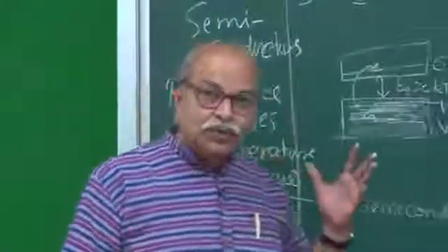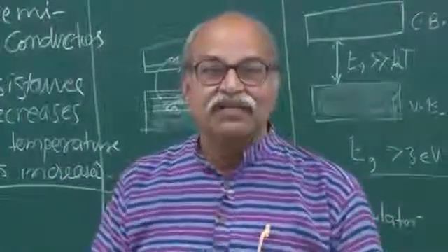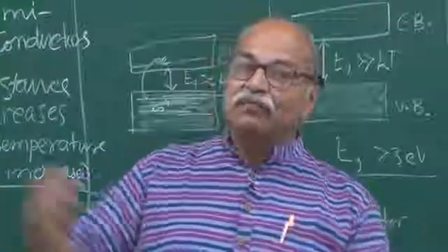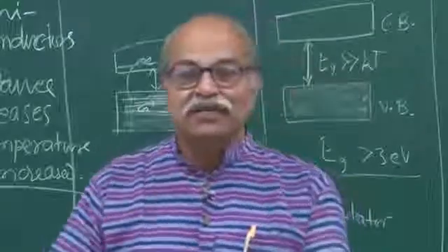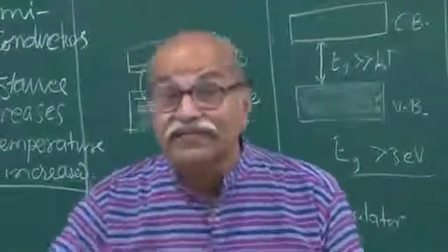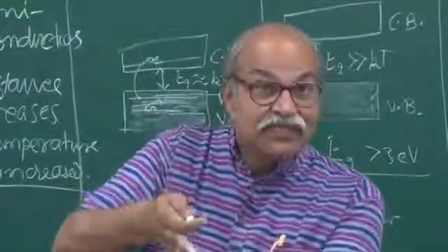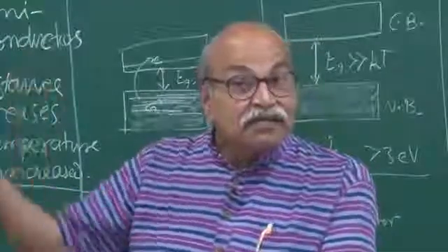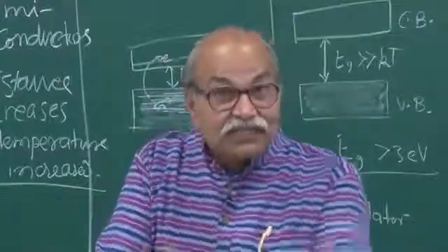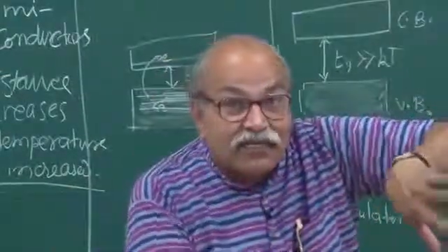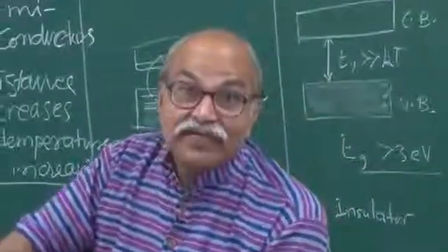This can be used to identify experimentally which material is a conductor and which material is a semiconductor, or if in some process there is a transition from metal to semiconductor or metal to insulator, going towards insulator. If there is some kind of transition, that transition can be identified experimentally by looking at the temperature dependence of the resistivity, and you can identify when it was in the conducting zone, and when it becomes semiconducting or insulating.